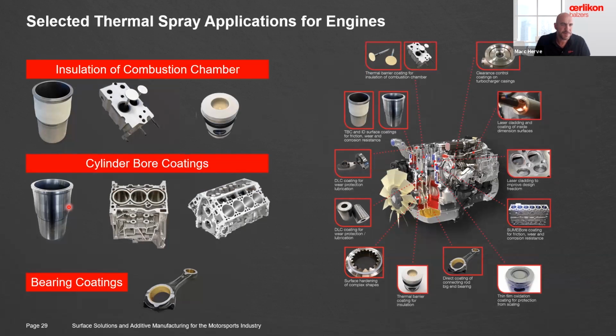For the thick film application, we talked about the SUMEBore coating before on the liner, but there are a lot more applications depending on what you're looking for. We can look for more thermal barrier processes and applications, for example, on the head or on the piston crown. There is a lot of possibility. So the SUMEBore is really on the inside of the liner. And for very severe applications, we can do the coating also on the inside of the connecting rod to be less abrasive. And there is a lot of things on the engine where we can apply the coating. But again, between the thick film and the thin film, I would say that these coatings are not really in competition. They are more complementary simply because they have different properties today.